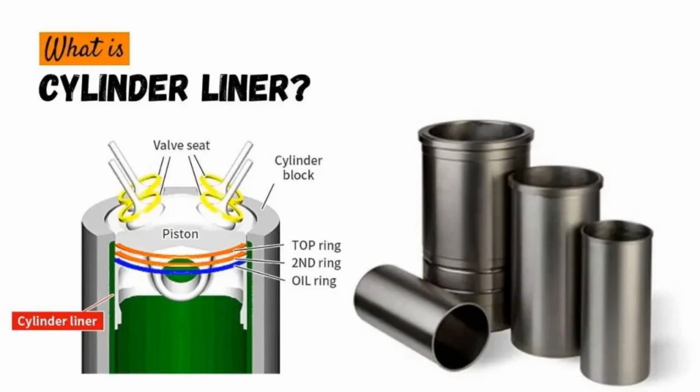A little later, as technology progressed, engineers switched to a procedure in which the liners were not pressed in, but cast around the block. The cast iron liner resembled a small insert that was melted into the aluminum. As a result, the strength was increased, but further pressing out became impossible. That is, the motors lined with such technology became unrepairable. Thus, the period of disposable internal combustion engines actually began. Gradually, manufacturers completely abandoned cast iron liners, ceasing to use them in aluminum blocks.